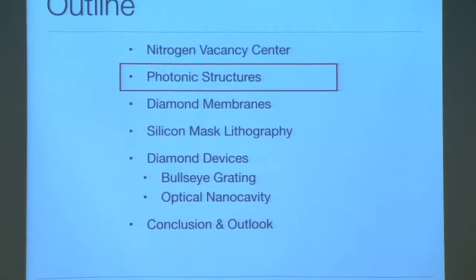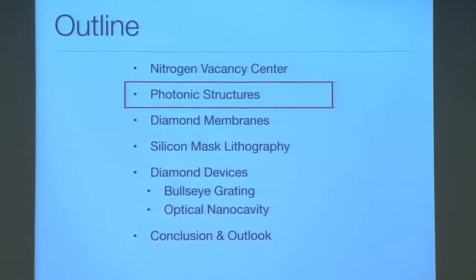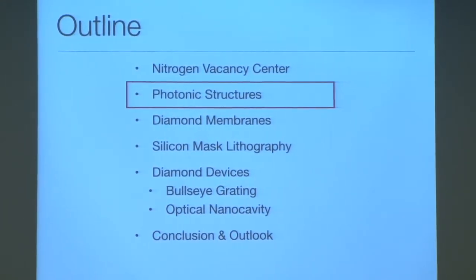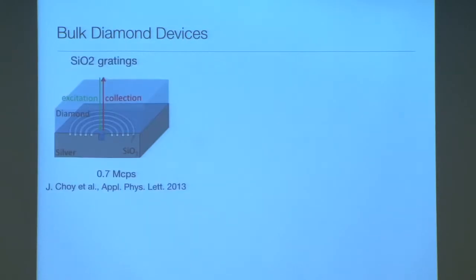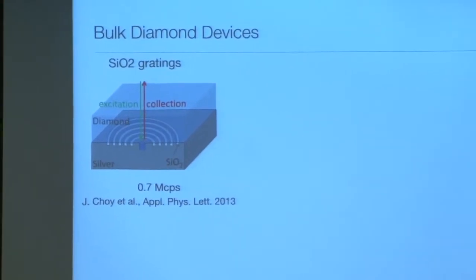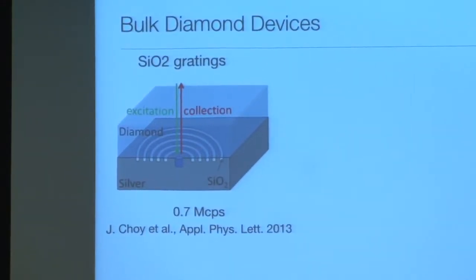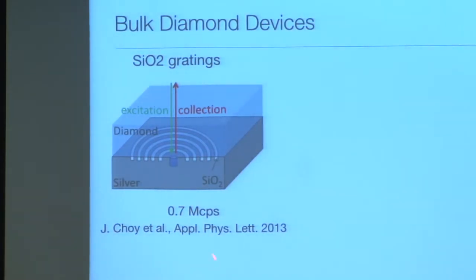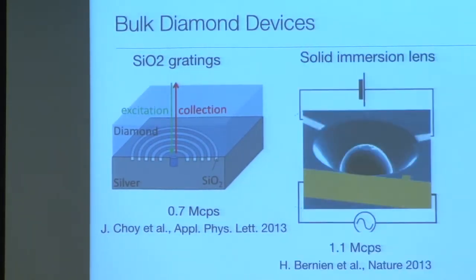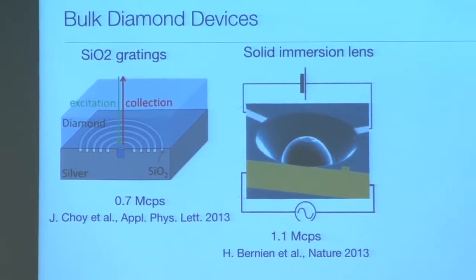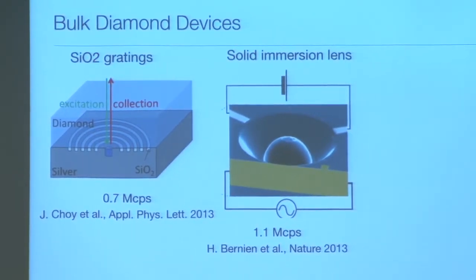The improvement of NV optical property can be achieved by fabricating diamond nanostructures. Many research groups have pursued different ways of fabricating photonic structures in bulk diamond. For instance, this one is a silicon dioxide grating embedded in a silver mirror, which helps to excite and collect the photoluminescence from a single NV center. Their collected count rate is about 0.7 megacounts per second. And this one is a diamond solid immersion lens, which gives 1.1 megacounts per second.